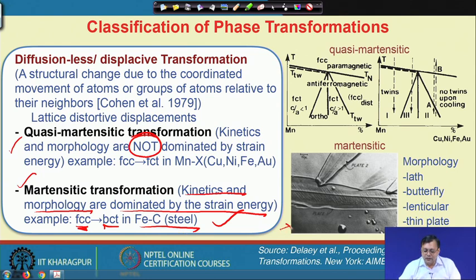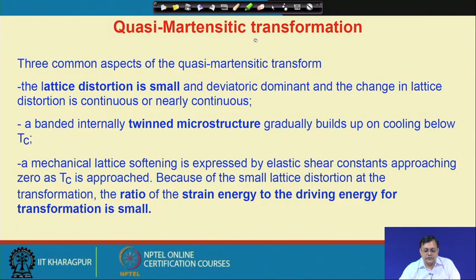I show you here one of the microstructures of such martensite. Here this is a martensitic plate, and this is, let us say, the parent austenite, and this is body centered tetragonal in an FCC. These are all martensitic plates. So far we have seen in the textbook that these could be lath type or plate type. However, there are also two other types of martensite morphology people have observed. In total there are 4 different types of morphology observed. One is lathe type, another is the butterfly type, one could be the lenticular type, and another could be thin plate type. This morphology is very important, and it also depends on how these structures evolve.